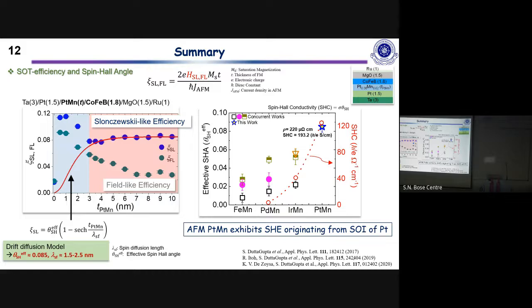So if you take these several different members, starting from iron manganese to platinum manganese, this is our data. And then you also take the different data available in the literature, and you see that there's a clear trend. The trend shows that depending on the spin-orbit coupling of these non-magnetic metals such as platinum and iridium, there is an increase in the spin Hall angle. So the more spin-orbit coupling of this non-magnet, the larger the spin Hall angle.